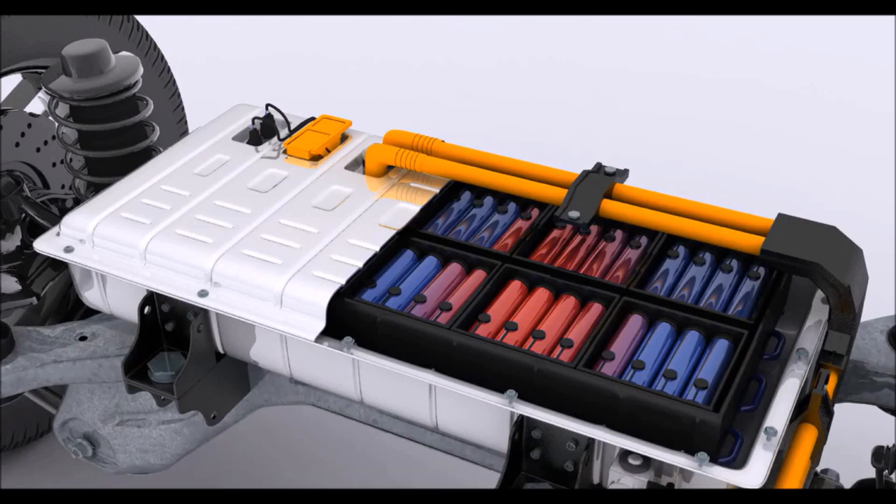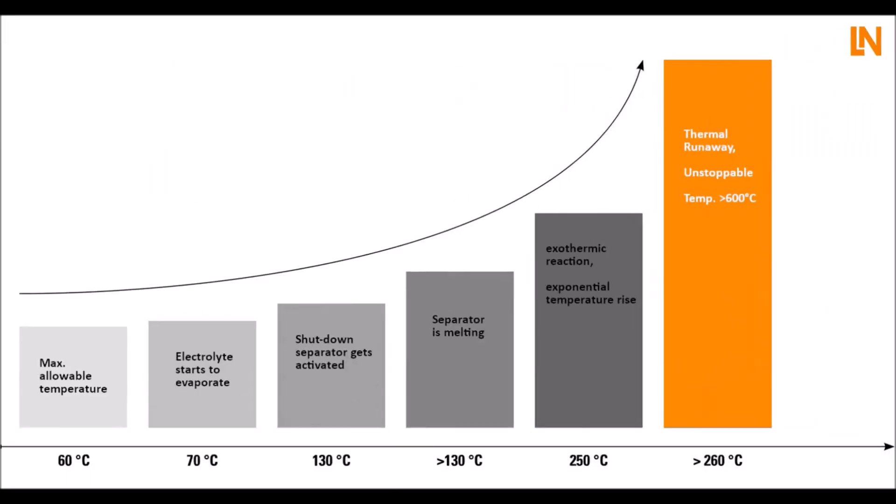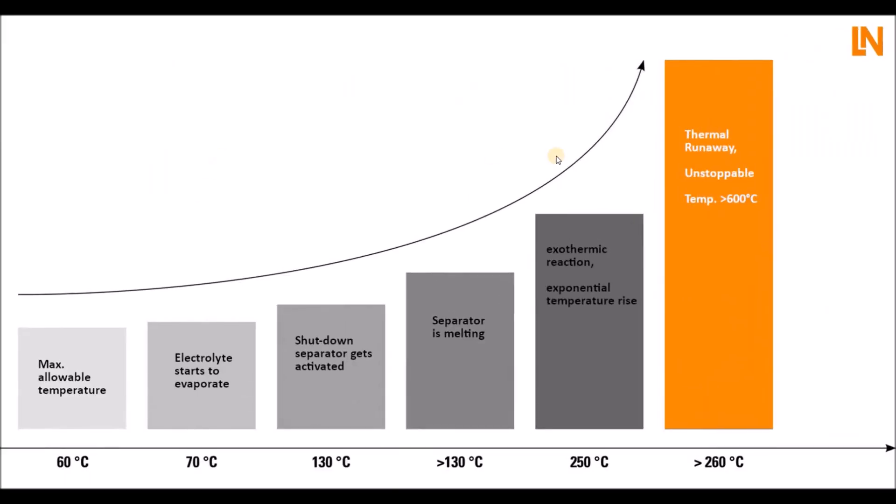What does it mean, a thermal runaway? A thermal runaway is not just appearing when your car is just at home and nothing happens to the car. A thermal runaway can appear, for example, when there is an overload from the electrical side. This is why it happens a few times when you charge the car, especially when you charge it at very high currents, high power charging. Now and then the electrical load was too much, and the cell was heating up and went into a thermal runaway.